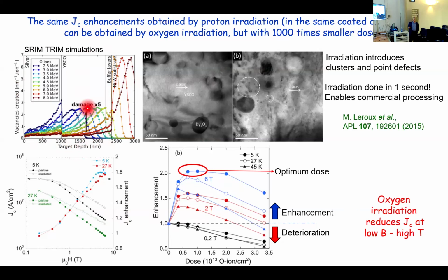We try to put the Bragg peak in the center of the YBCO layer to maximize the damage. And then in one second, we could produce enhancements by a factor of 2 at 6 Tesla. Of course, we don't see orders of magnitude increase in Jc like we have in the single crystal, because the Jc here is much higher than in the single crystal to start with. But it's still a factor of 2. Manufacturers will kill for that.